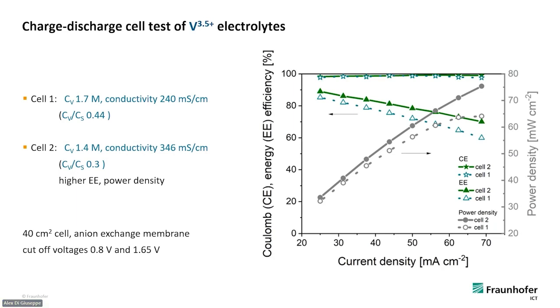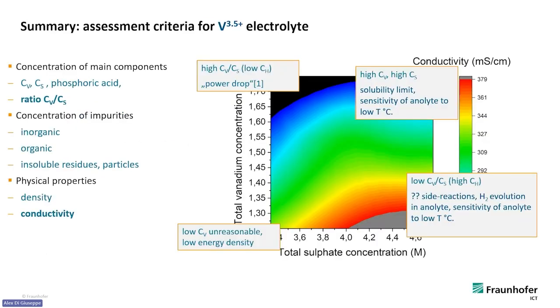So in general, you could say, even though you're diluting the electrolyte from 1.7 to 1.4 molar, you gain thermal stability, you use less vanadium, but you have a better capacity utilization. Actually, we don't lose energy. So this was really surprising for us. Our diluted electrolyte has the same practical capacity as the regular electrolyte. And so we actually made an electrolyte which is more temperature stable and costs less. So this was quite interesting to see.